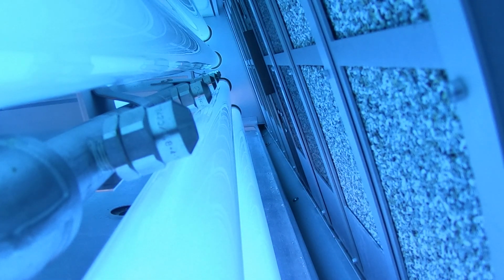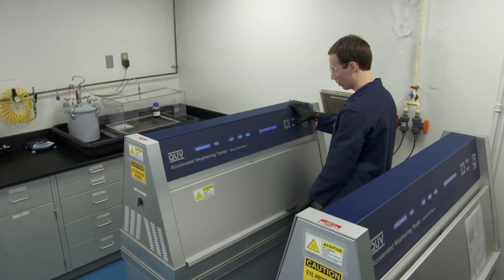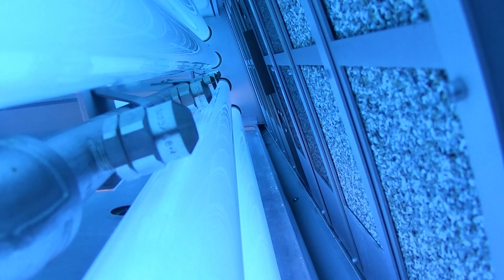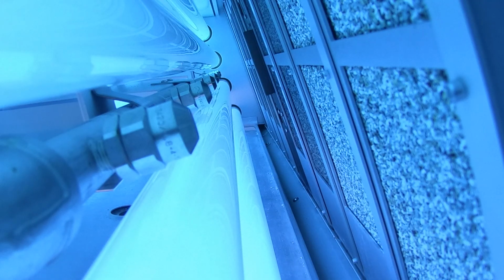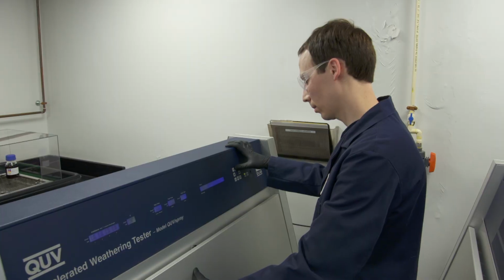So how long will a test like this run for? With this testing, we're actually putting UV sunlight for about 48 hours on the sample. However, we can do various hours for longer times. We'll do thousands of hours to simulate years of exposure. Right, so this test is typically maybe days and potentially a month. Yes, exactly, or longer. Got it. So while the UV lights are on, we're also heating the chamber, and we heat the samples up to about 140 degrees Fahrenheit.